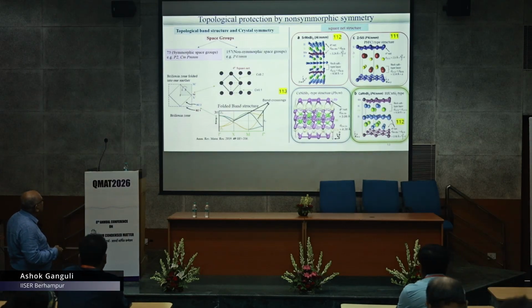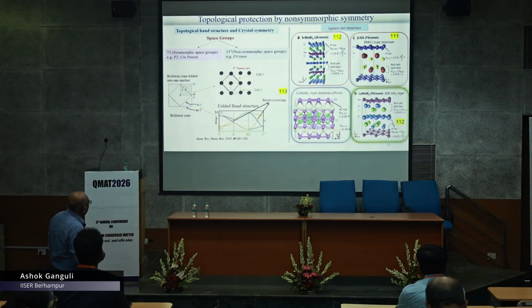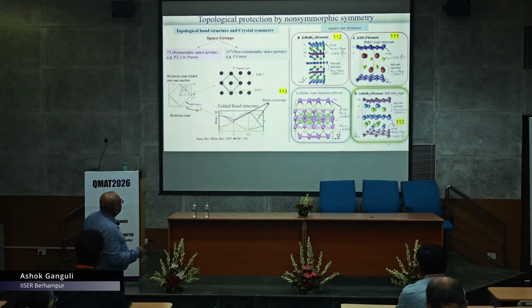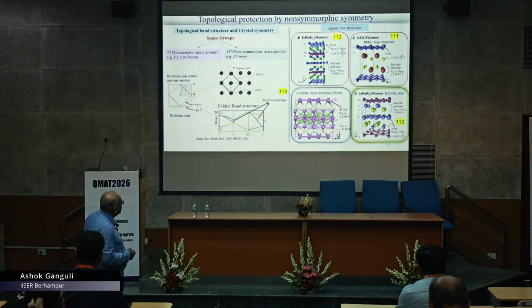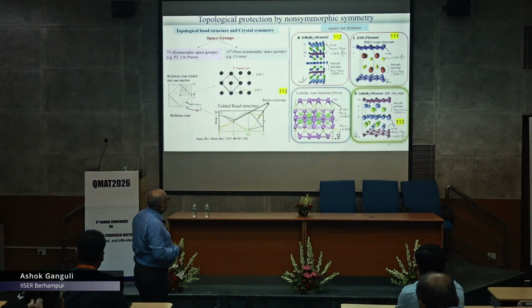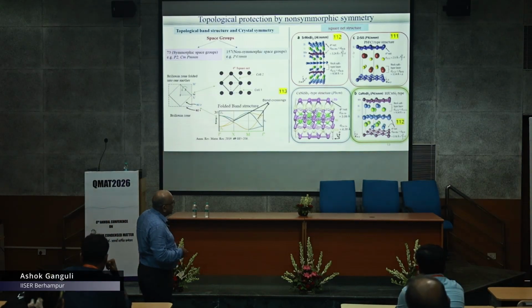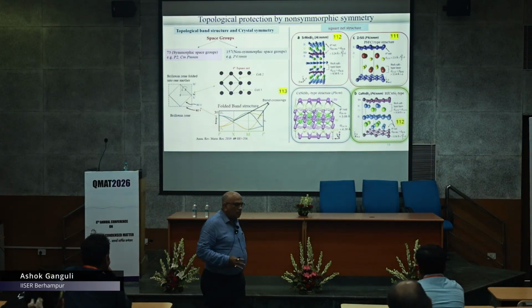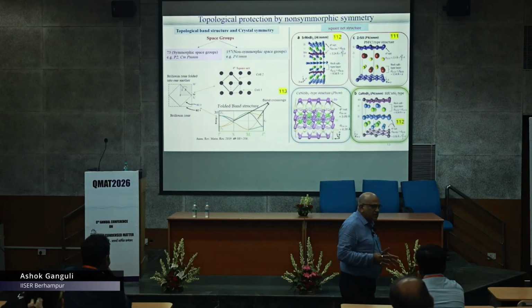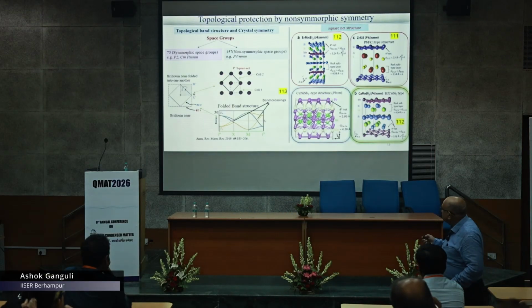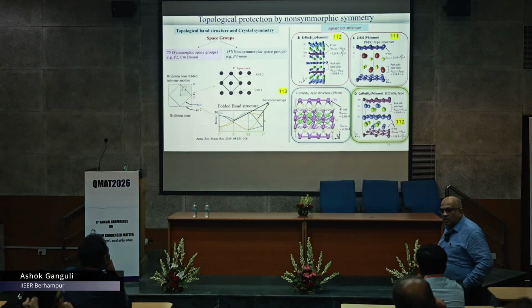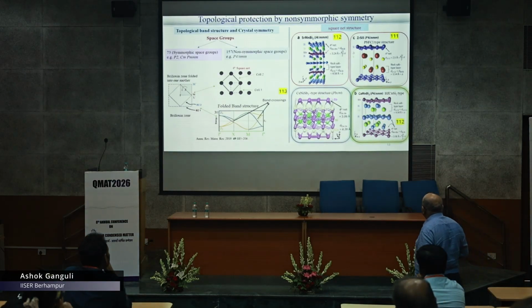So this is another slide to show what happens in this 4x4 structure. You have this folding of the Brillouin zone, and you have these band crossings possible. Here I show 4 structures. Of course, 2 of them are similar. Both of them are 1,1,2 structures: strontium manganese bismuthide and calcium manganese bismuthide. Both of them are referred to as the HfCuSi2 structure, because HfCuSi2 was the first structure which was solved, structurally, long back. But there are hundreds of compounds which have this 1,1,2 structure.